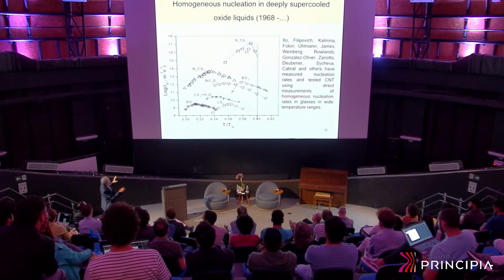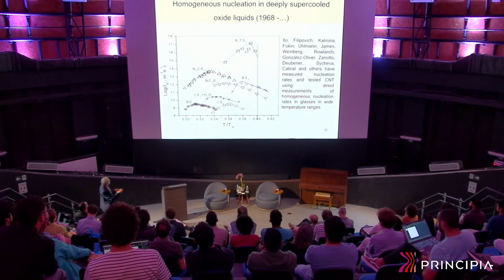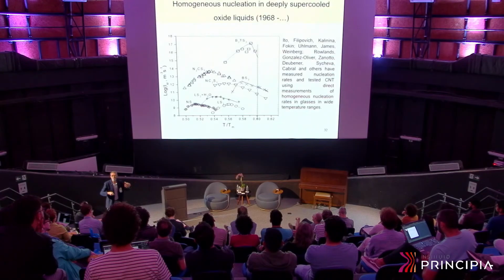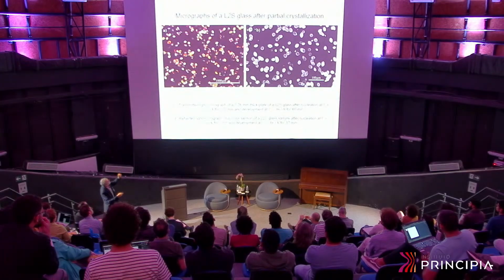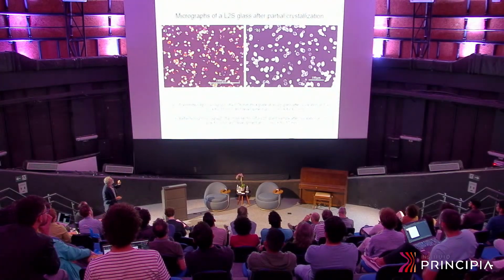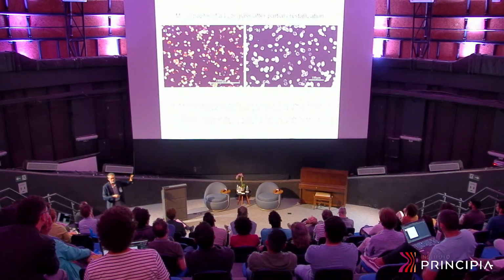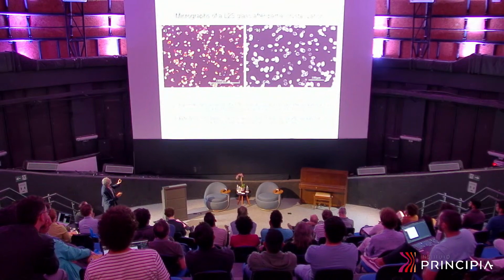In this area, people have measured nucleation. This is nucleation rates versus temperature divided by the melting point, just to show them in the same plot. You see, very nice nucleation rate data measured over wider ranges of temperature, which would provide, in principle, better tests. And these are beautiful crystals that we are able to produce and count precisely in different glasses. This is from my lab, actually.